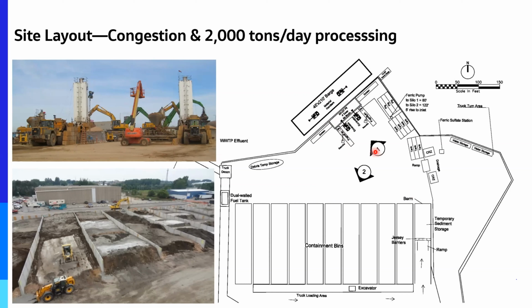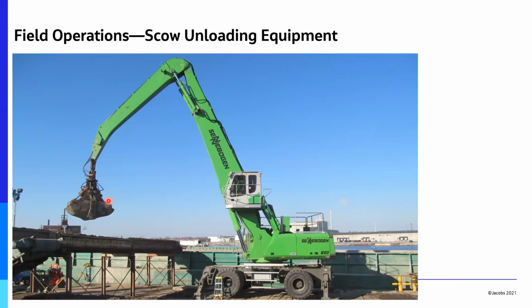So this is the backside. This is looking at the two excavators unloading. This is the pug mill system, and this is where the solidified solids come out, and then they are taken to the storage bins, each one of those being 1,700 cubic yards. That's what this picture is. What you see in the background is an excavator sitting on an elevated platform that can reach back into that treatment cell, take the material out, swivel around 180 degrees to the opposite side, and put the material into a truck.